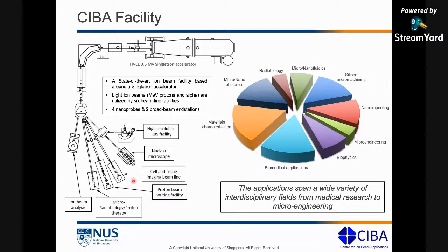Then we have the cell and tissue imaging beam line. Now this beam line is not very different from this one. The only difference being that here we can put in live cells. So this setup here is an open air setup, where we put the cells in open air, not in vacuum. Whereas here the cells go in vacuum, so they are pretty much dead. So we have cells, cell tissues, or cell membranes that go in here. And what we do is we use proton beams or alpha particle beams to image these cells, map these cells for certain elements that we want to map out, or certain contaminants that we want to map out. This one here is a nuclear microscope.